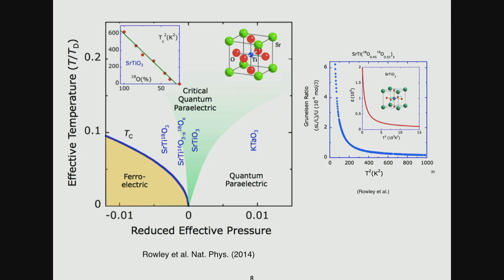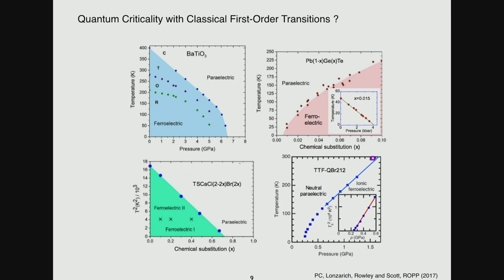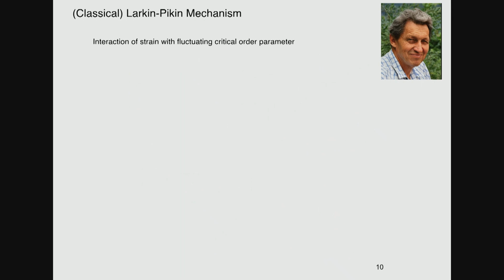Okay, so what's this material doing having quantum criticality when it's usually first order? Turns out there are a number of other materials. There's even barium titanate. It turns out if you put barium titanate under pressure, there's a lot of indication, this is still early days of the experiments, but there are a lot of indications that there's quantum critical behavior, and there are a number of other materials that are starting to be studied at low temperatures and high pressures, which seem to indicate first order transition. We know they're first order classically, but when we apply pressure and go to low temperatures, they seem to have quantum critical points. So the question is, what's going on? So this is our motivation.